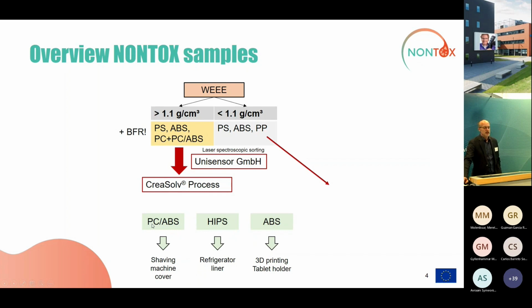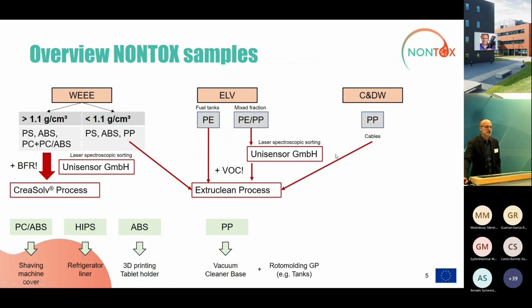Come to that later. The basic idea behind this was to produce PC-ABS, PS, and ABS in quantities high enough to produce demonstrators later in this project. But this was not the only kind of samples that we characterized and identified as suitable for the project. We also went into end-of-life vehicles. Here we had identified fuel tanks and mixed PE-PP fractions. These were not so high in brominated flame retardants, so the highest load of contaminants were the VOCs in here. This is why we decided to treat them by the Extruclean process. This will be presented in the next talk.